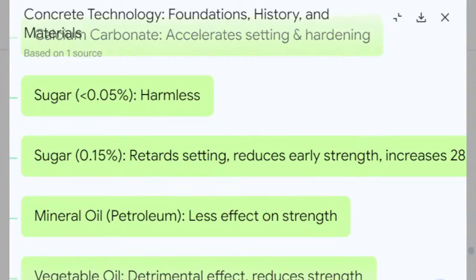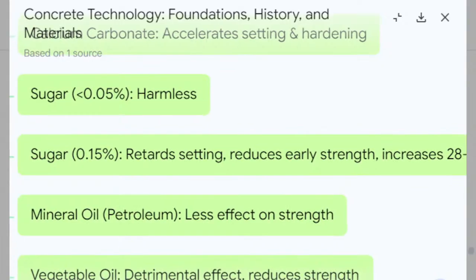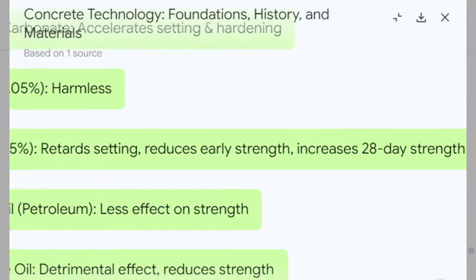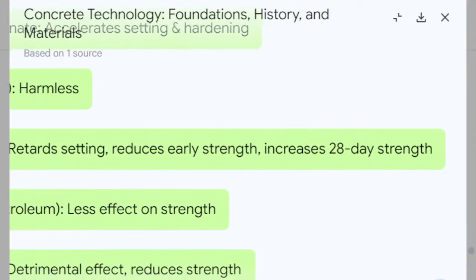Sugar, like from a spilled drink. Could be. Or maybe from industrial contamination. The effects are highly dependent on the amount. Up to about 0.05% by weight of cement, it has very little impact. However, if it's present at around 0.15% by weight, it acts as a strong retarder, significantly delaying the setting time and reducing the early strength gain. But, and this is the really intriguing part, it actually increases the 28-day strength.